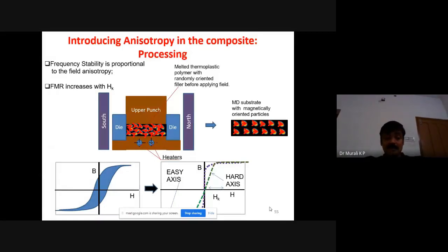It will increase the field. That field will enhance the change of the easy axis of magnetization to hard axis, and it will impart more mu, because even after removing the magnetic field, it will retain some orientation, so that it will enhance the initial permeability compared to a random orientation. So this is called introducing anisotropy in the composite.